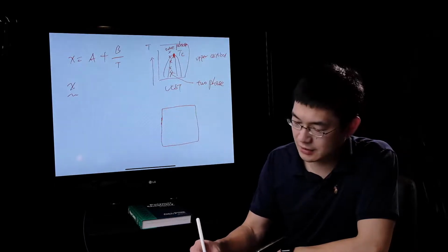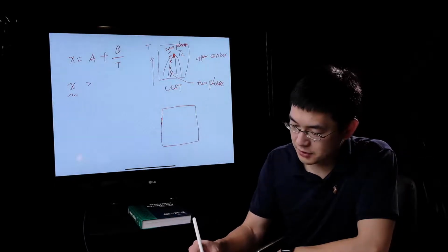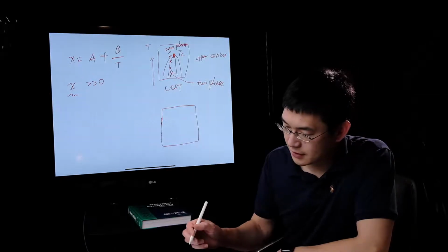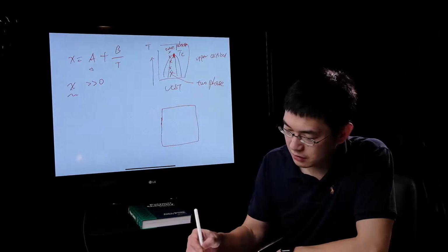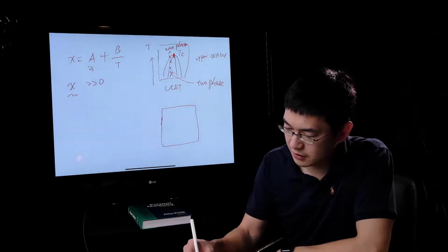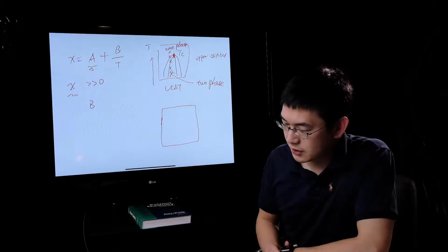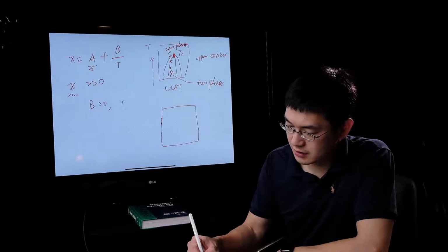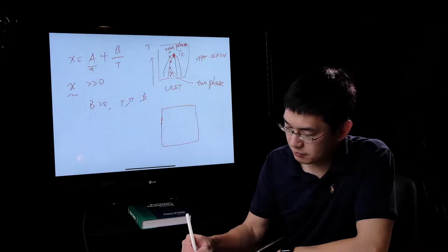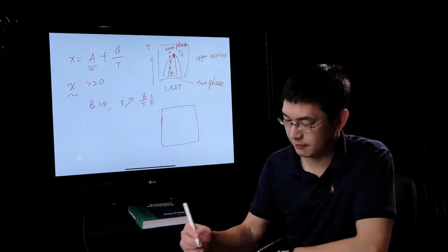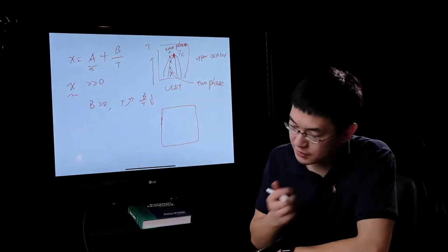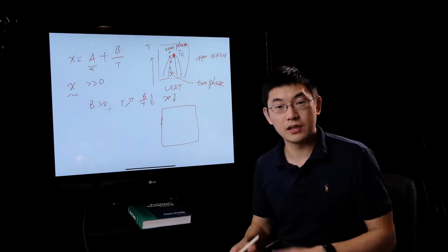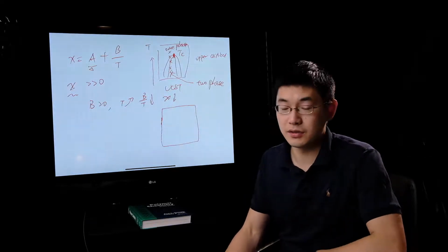As we know, if chi is much bigger than 0, the system will not mix easily. So it doesn't depend much on the A constant, but it depends on B. If B is larger than 0, when the temperature goes up, B divided by T will go down. And this means overall chi will reduce. So your system will likely behave like UCST.